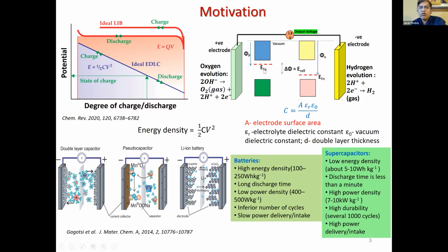Basically, currently all the aqueous supercapacitors, or the supercapacitors or storage devices which use a water-based electrolyte, two things happen. At the positive electrode, there is oxygen evolution, and at the negative electrode, there is hydrogen evolution if you exceed the voltage beyond 1.23 volts. So that is the window you use. But that is basically because this is the work function of the material, and once you exceed this, oxygen evolution takes place, and once you exceed this Fermi energy level of the negative electrode, hydrogen evolution takes place.